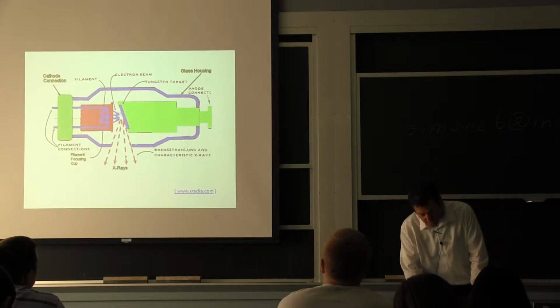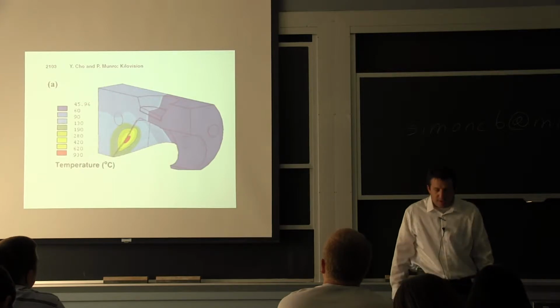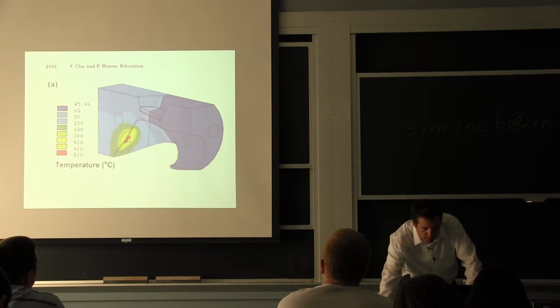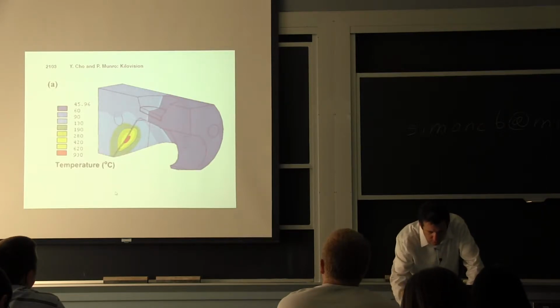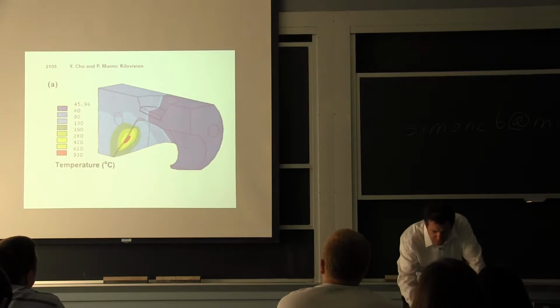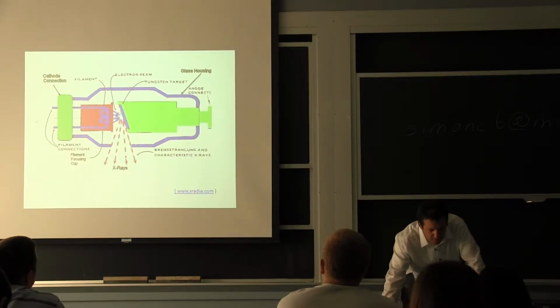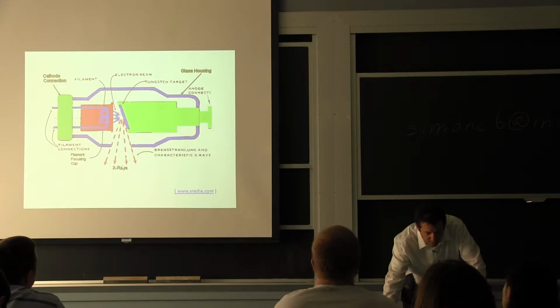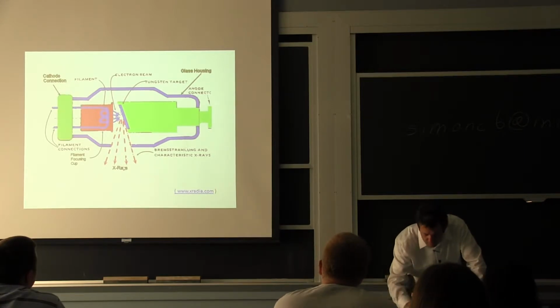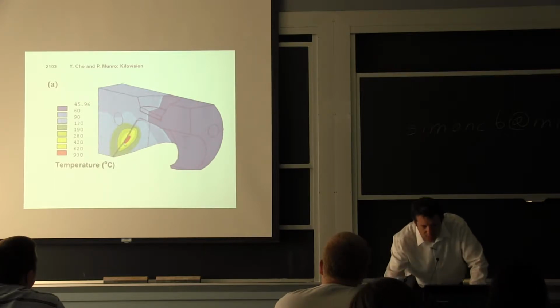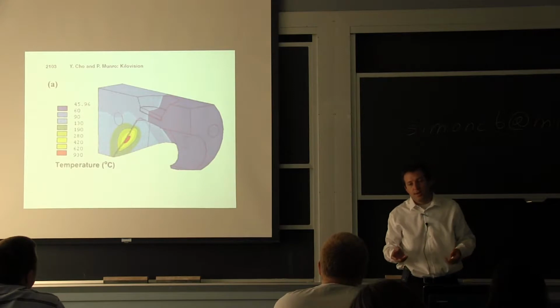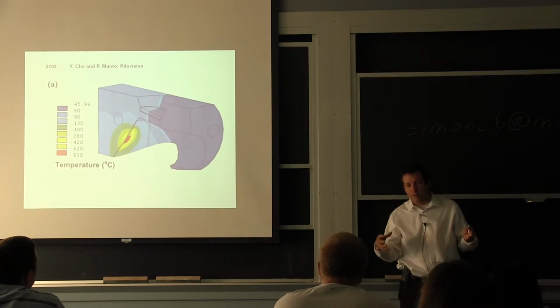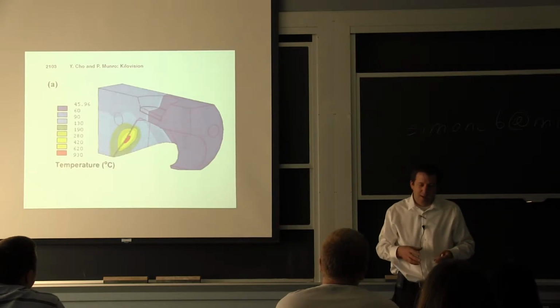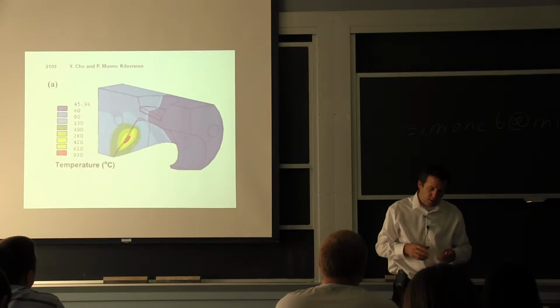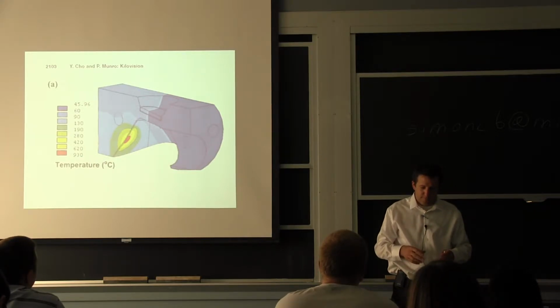So we got involved and essentially tried to work not only on reducing the peak temperatures. So here you're looking at the temperature. The target is at an angle. The reason is, say the electrons are coming from left to right here, and then they emit the X-rays at an angle, and that's what's used here for imaging purposes. So if you try to minimize that surface temperature here, that's already a starting point. The other thing was to try to make it a little bigger, and also in the end to try to not have it all centered.